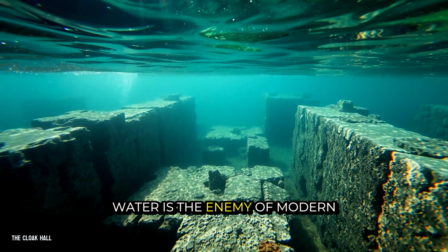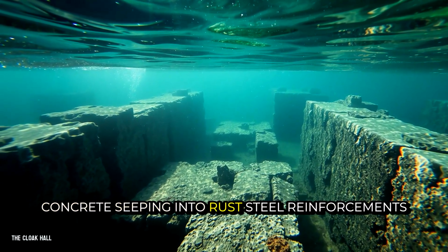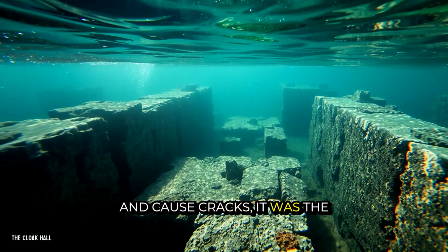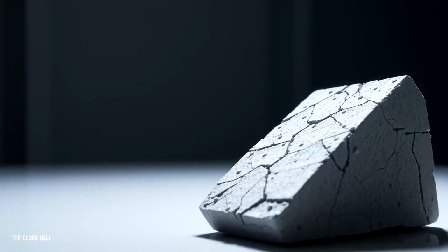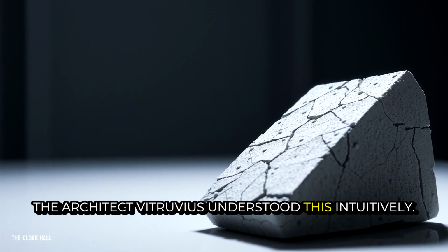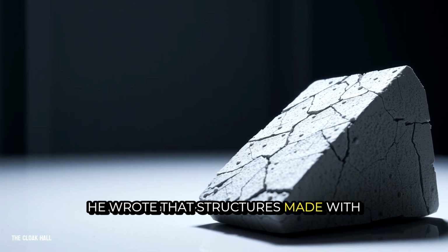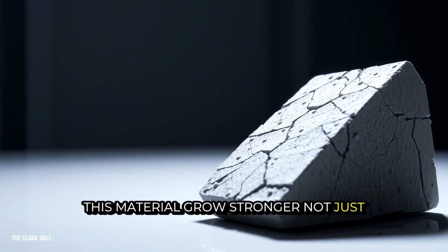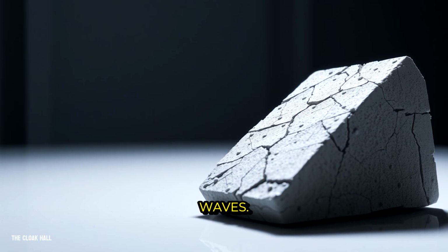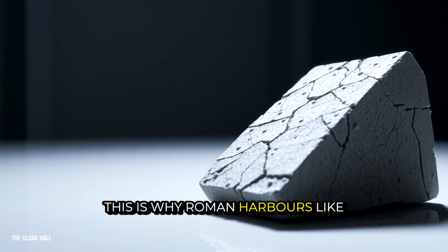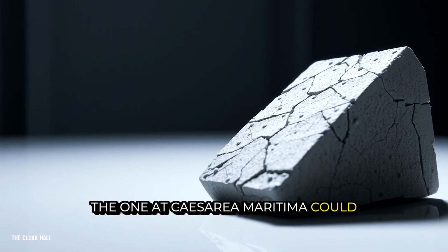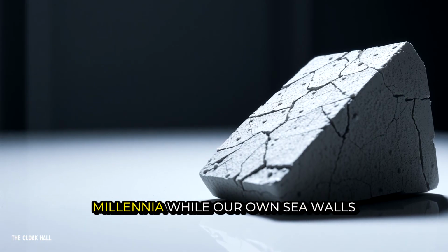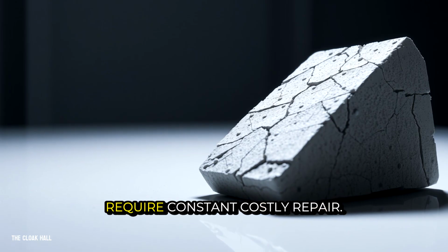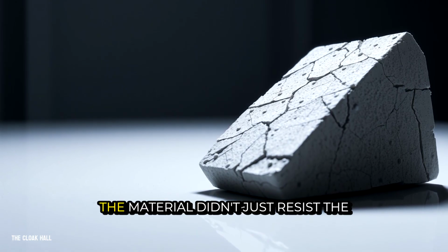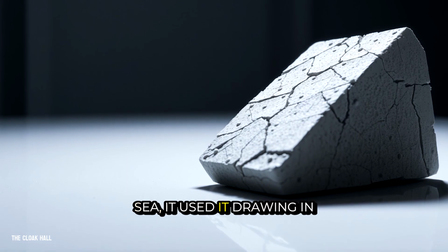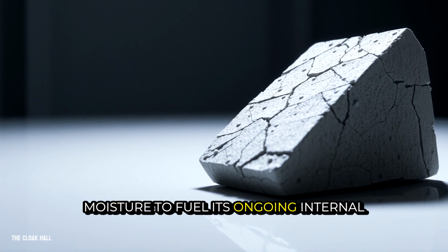While water is the enemy of modern concrete, seeping in to rust steel reinforcements and cause cracks, it was the catalyst for Roman concrete. The architect Vitruvius understood this intuitively. He wrote that structures made with this material grow stronger not just on land, but remarkably beneath the waves. This is why Roman harbors, like the one at Caesarea Maritima, could defy the relentless saltwater for 2 millennia, while our own seawalls require constant, costly repair. The material didn't just resist the sea, it used it, drawing in moisture to fuel its ongoing internal growth.